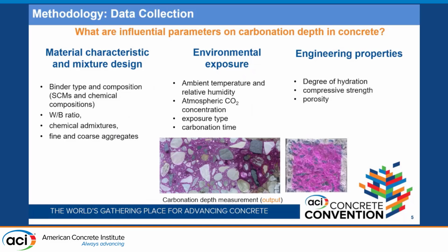The first step was to do a round of literature review to see what types of parameters influence carbonation in concrete. If we classify those parameters into three main groups, the first group is material characteristics and mixture design: the binder type and binder composition, different types of SCMs, their reactivity and chemical compositions, water to binder ratios, other mix constituents, perhaps chemical admixtures, or fine and coarse aggregate contents. These parameters could have different levels of influence on the carbonation process in concrete.